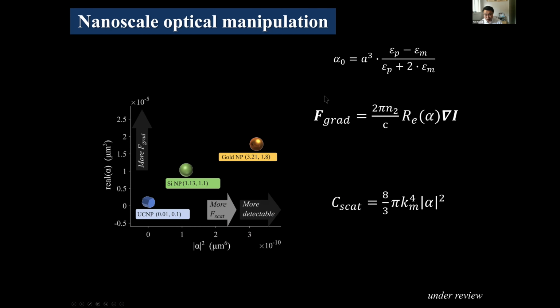So in relation to nanoscale trapping, the one parameter of the polarizability is really important, because traditionally we can only trap things with a contrast of the polarizability, or a contrast with the permittivity. Your surrounding material is usually just water, so if your particle has the same refractive index, you pretty much couldn't trap it.